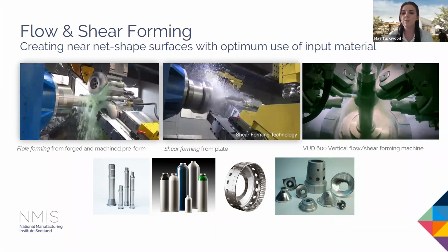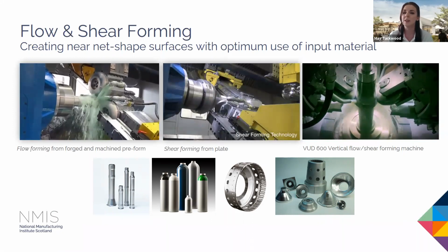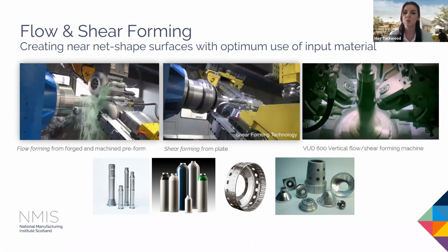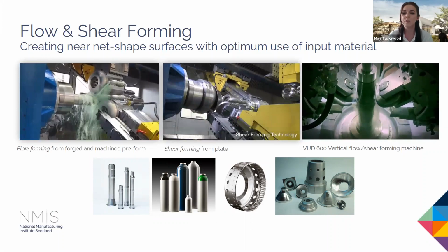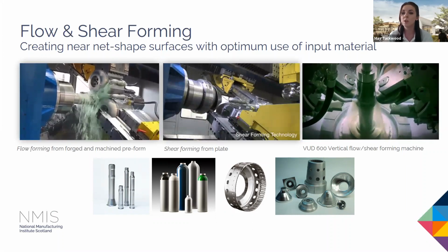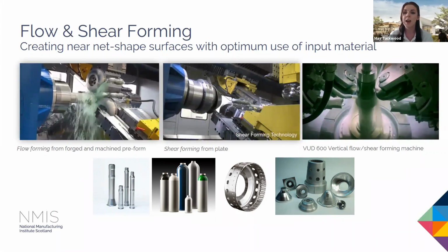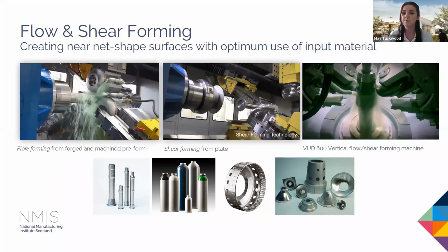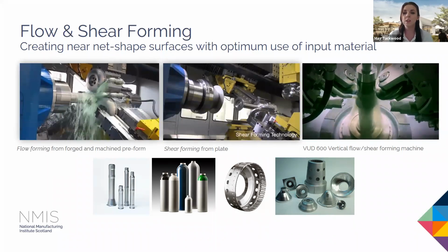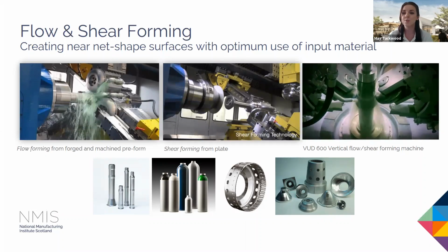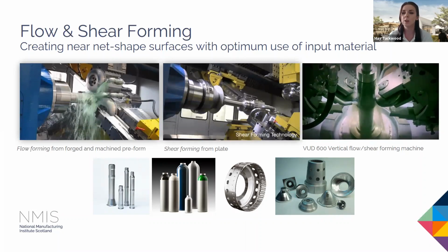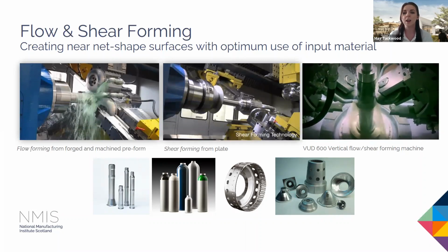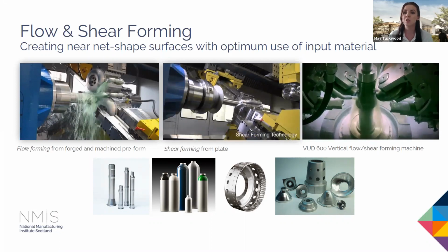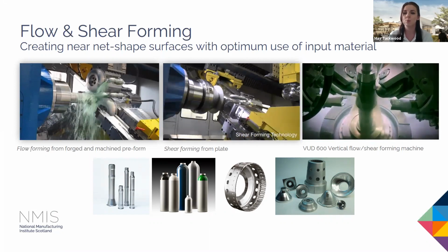We can also create varying wall thicknesses, and this is really the types of components that this process is best suited for. Those types of features may be used for mounting other components within the assembly where you require higher thickness and higher strength in that region. But also often the formed surface is left as formed with no further machining required. So in terms of your manufacturing process as a whole, it's much leaner. We can start to reduce steps in that process.